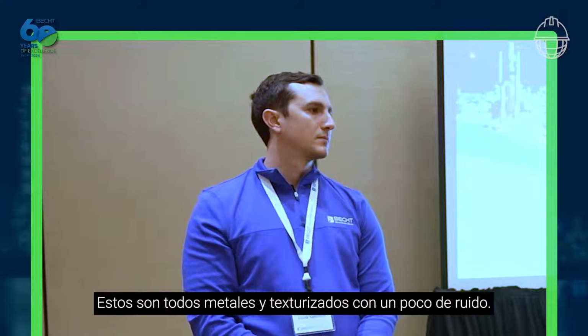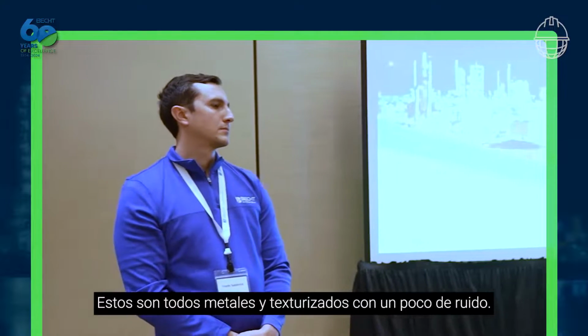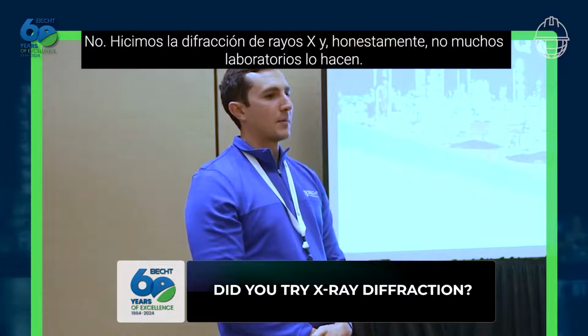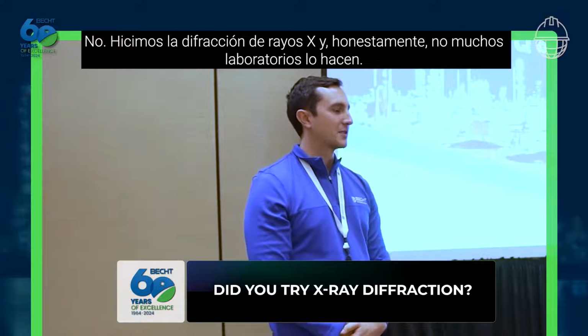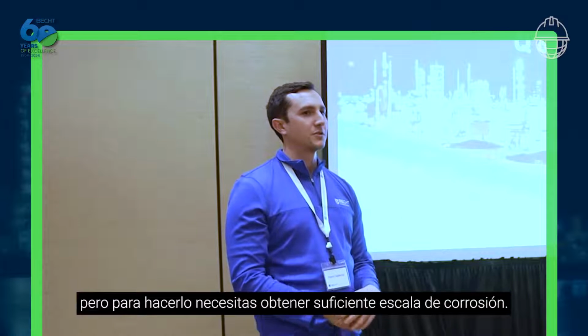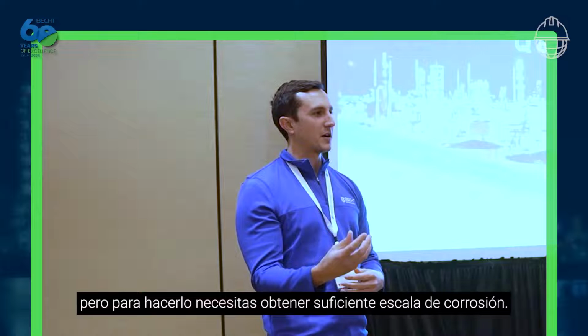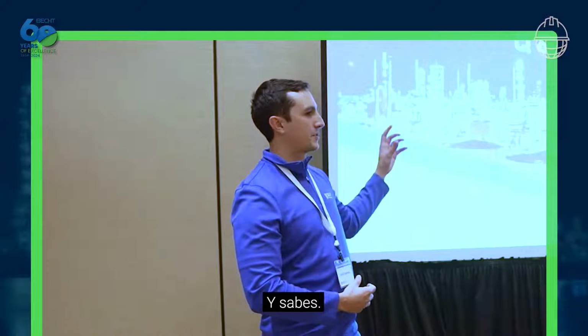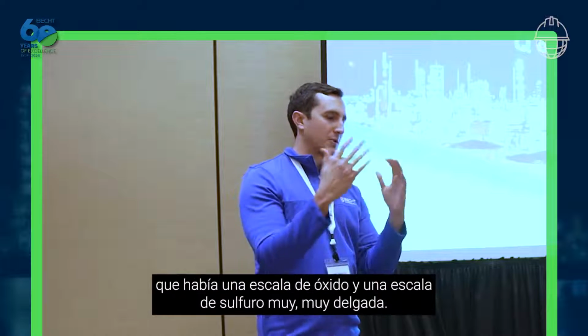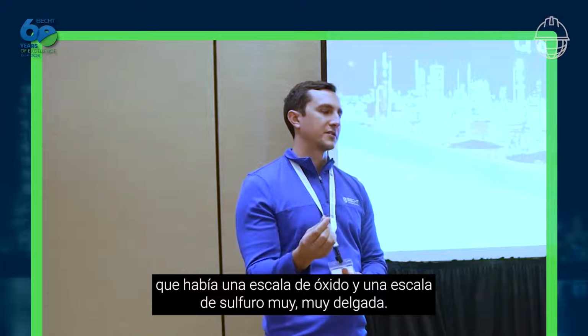Brian? Did you attempt X-ray diffraction? No, we didn't. X-ray diffraction, honestly, not a lot of labs do it. This lab can do it, but to do so, you need to get enough scale off of it. And when we did the EDS analysis, it was pretty clear that there was an oxide scale and a very, very thin sulfide scale.